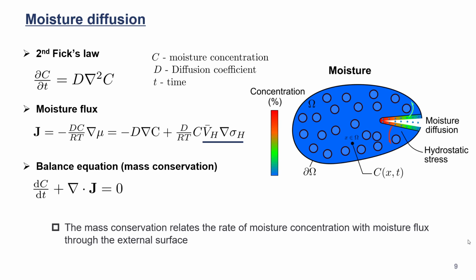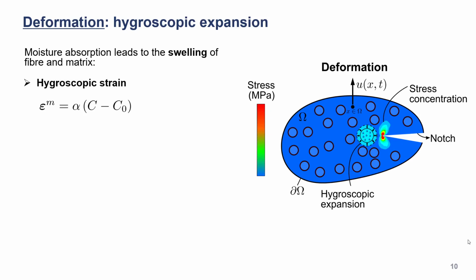Following that, we can derive the balance equation, which is based on the mass conservation law. This relates the rate of the moisture change with the moisture flux through the external surface. Move to the deformation problem. The deformation problem basically means if the moisture is absorbed into the material, it can lead to the swelling of the fiber and the matrix. We need to calculate this hygroscopic strain by considering the expansion coefficient times the change of the concentration. In our Hooke's law, when we calculate the Cauchy stress, we need to exclude that hygroscopic strain.